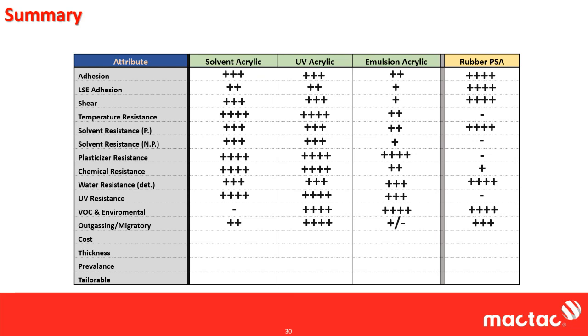The oil can outgas. Emulsion acrylics have a lot of outgassing. It's a lot of all those other additives that are in there. UV acrylics are the best for this, and solvent is going to have a lot of the unreacted monomer that's in there. So again, electronics, certain automotive specs, certain medical applications. If you need a really clean adhesive, nothing is going to outgas. UV is really the best bet.